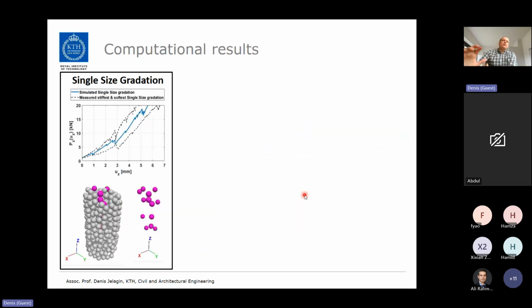So I'm almost on time. I'll just show some final examples of computational results. Here we have simulations of particle breakage for single size unbound material, and those are the ones which were used to determine input parameters for the failure law. On top, you can see the force displacement response. The blue line is the numerical model, and the dashed lines are experimental results. And we have the distribution of fractured particles in the material.